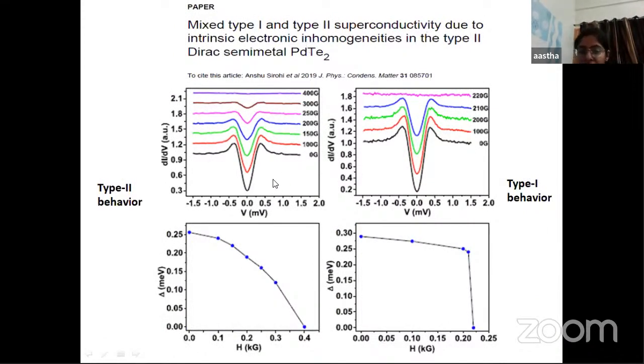In these scanning tunneling spectroscopy measurements, we looked at the magnetic field evolution at different locations. What we observed is that for certain spectra at certain locations, the superconducting energy gap was found to evolve smoothly with the magnetic field, which indicated type 2 behavior, while for other regions, where type 1 superconductivity was reported, the spectra showed a first-order disappearance of the superconducting energy gap. So this part revealed type 1 superconductivity, while the smooth evolution represented type 2 superconducting behavior.